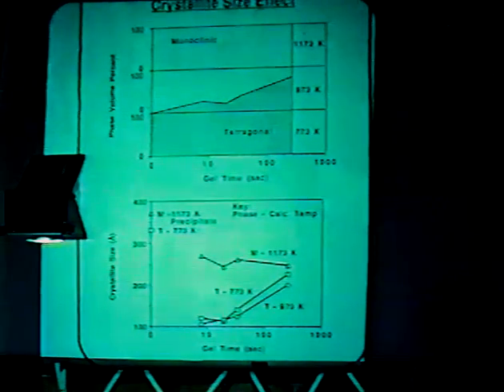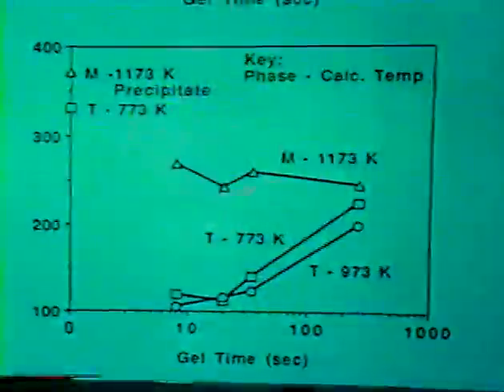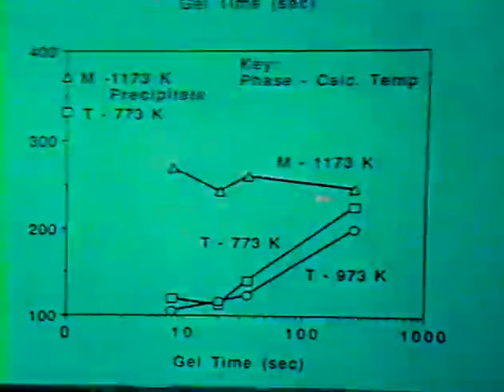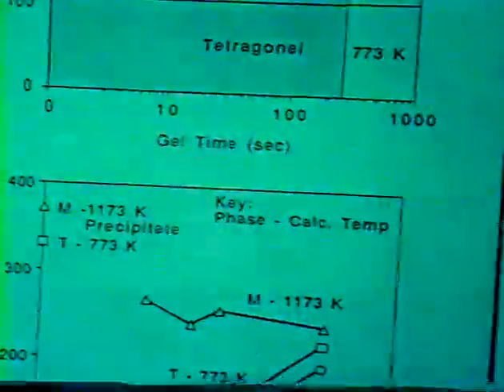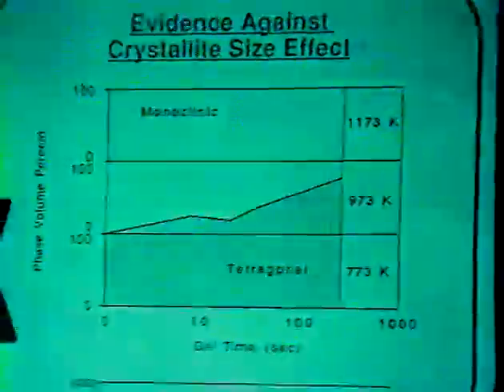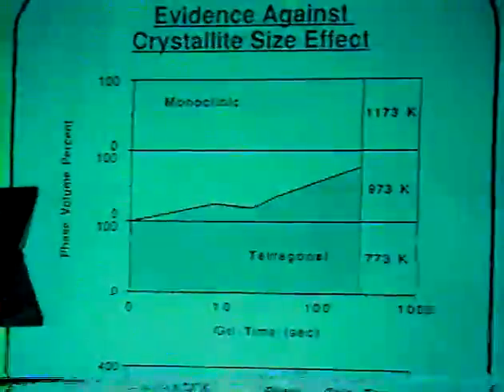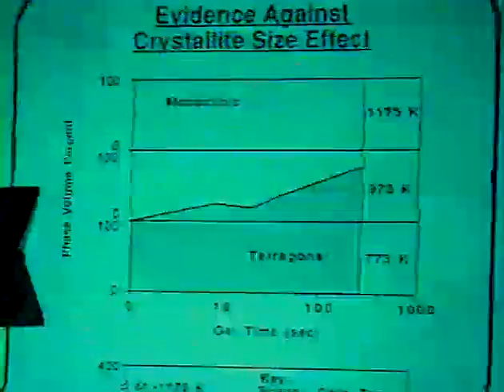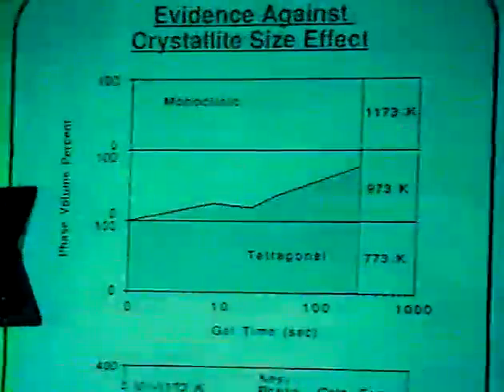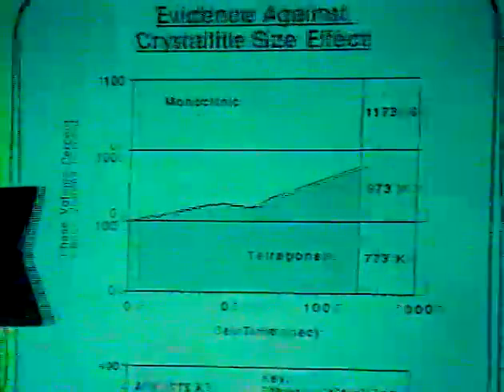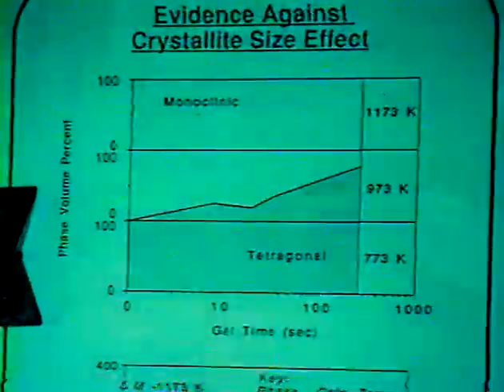First, I want you to focus on the bottom panel. With gel time now as a variable that we can systematically vary, we look at the crystallite size determined by X-ray diffraction line broadening as a function of gel time. Okay? At zero gel time, basically we're looking at a precipitated sample, and then we have over this plot 4 different gel samples prepared as aerogels in which we vary the gel time. We took all these samples to 773, 973, and 1173 K. We determined the structure by X-ray diffraction, measured the crystallite size by line broadening, and then found the following. First of all, for the precipitated sample, we could actually stabilize the T form, and this material actually has a larger crystallite size than some of the M form we stabilized by heating the aerogel up.